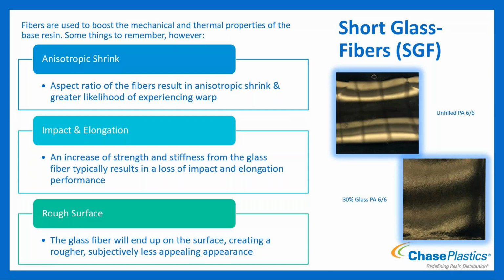And that's shown very clearly on the right-hand side. You can see the top one is an unfilled 6-6, so it's kind of nice and shiny. There are some fingerprints on it if you notice, but it is pretty shiny and easy to look at, looks kind of polished. Then you look at the 30 glass and you can see it's very much rough. It's hard to make out the lights, which is what's on the ceiling that's actually reflecting off the part, but it's difficult to make those out because the surface is so rough. It's not polished and allowing the light to reflect off it as easily. So keep that in mind, it is going to change the appearance.